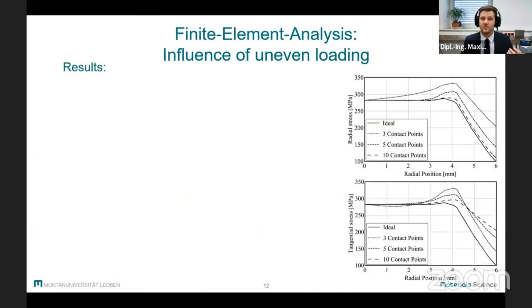In these results, we can observe a significant stress increase at, or rather close to, the loading ring radius. If the number of contact points is increased, then the ideal case will be approached.